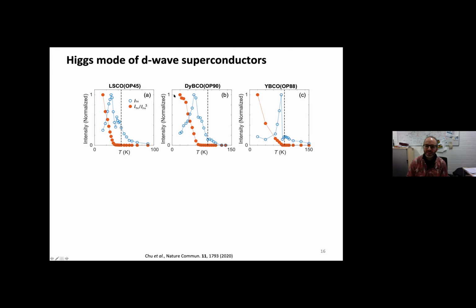If we look at this now for the other samples, we find very similar responses for all of these samples in the system. So far what we see is, okay, indeed, we can drive very, very strong Higgs modes, and we find that these Higgs modes are heavily damped in this material. The question is now, how strong is the damping? And for this, we now take a very, very simple model.